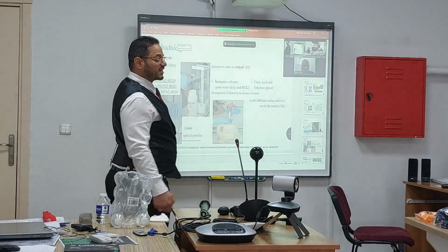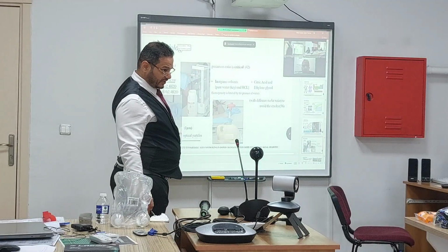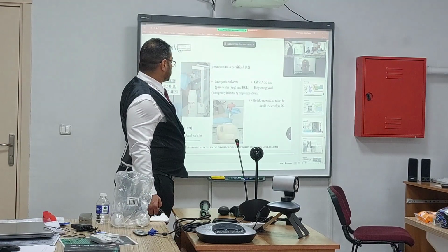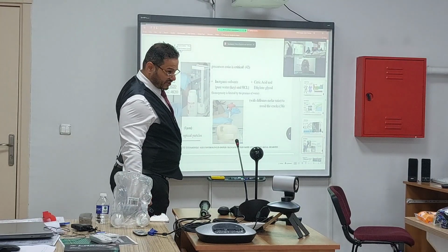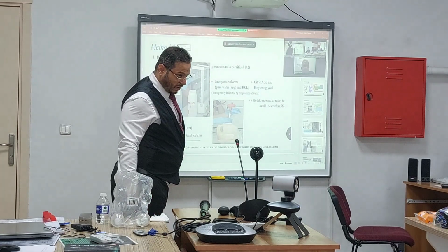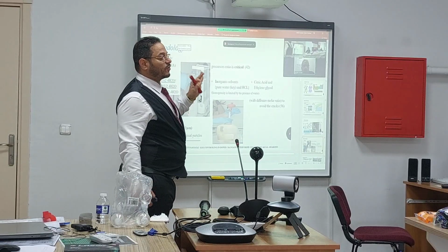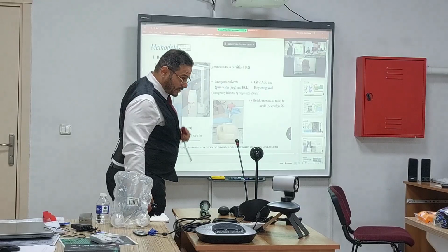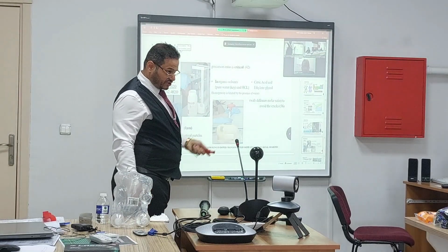Let me start with hydrolysis, with the inorganic metallic oxides, or the precursors: lanthanum oxide, strontium nitrate hexahydrate, calcium nitrate hexahydrate, and manganese nitrate hexahydrate, with some amount of water, hydrochloric acid, and, don't forget, the most important thing, the agents: citric acid and ethylene glycol.